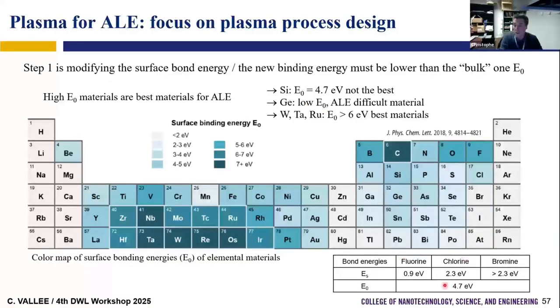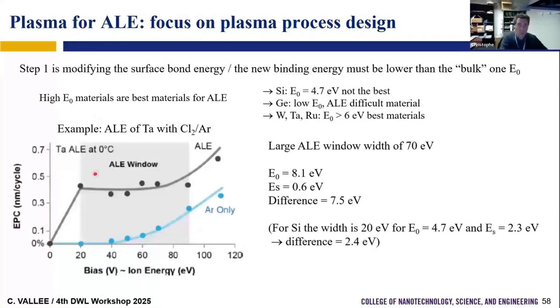So here's an example for silicon. For silicon, if you have only silicon atoms in the bulk, the energy is 4.7 eV. But if you do a chlorination or fluorination, you reduce the binding energy. So you will modify the sputtering threshold for the atom at the surface that is bound to fluorine compared to the atom in the bulk. So I took here the example of tantalum. Tantalum is very nice because we have a huge contrast between the surface binding energy if you do chlorination and the bulk. So the difference is very high. So you have a large window of energy for which you can sputter only the tantalum atoms that are bonded to chlorine, and you will not sputter the tantalum atom in the bulk.